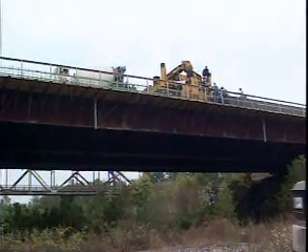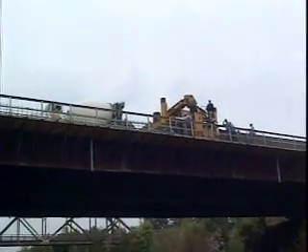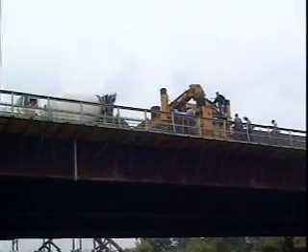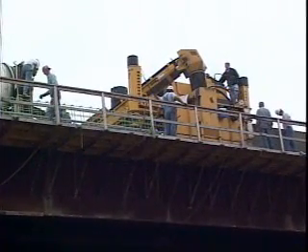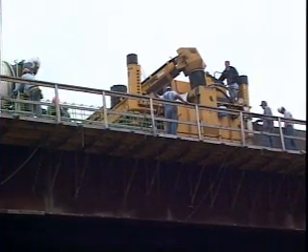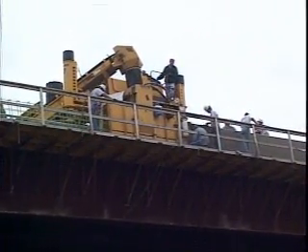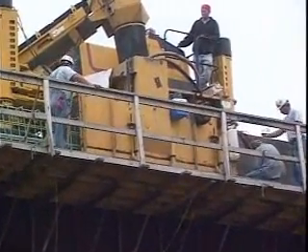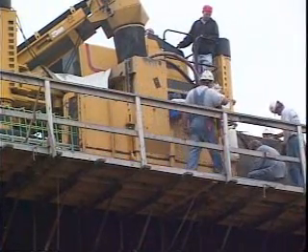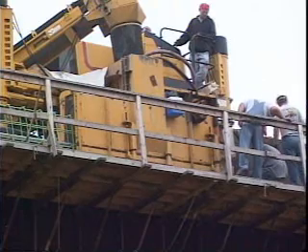The joints are sawed differently depending on whether you're on the cable span or on the approach span from the Illinois side. On the cable span, there's a saw cut approximately every 35 feet — one inch deep with a backer rod and silicone sealant over that. On the Illinois approach, there is a cut at the center of each cap, and then every 10 feet thereafter for a total of eight cuts at each cap.